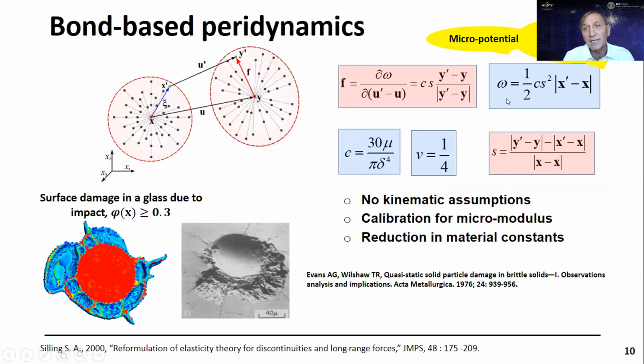For this particular material that Silling introduced in 2000, you have the microelastic brittle material. This is the micropotential, and C here is the micromodulus, that's known as the bond constant. So by taking the derivative of the micropotential, you end up with the force density vector F. And there are no kinematic assumptions. You need to calibrate the strain energy densities coming from peridynamics and from classical continuum mechanics to determine the value or the expression for the micromodulus. This is what it is in terms of the shear modulus, but there is a reduction in material constants. So depending on the dimension of the analysis, this Poisson's ratio is either 1/4 or 1/3 for plane stress.